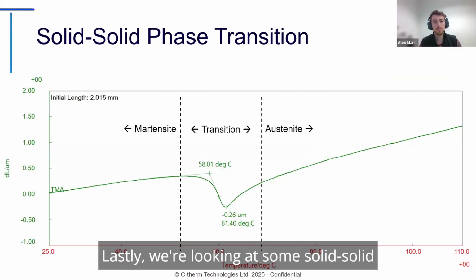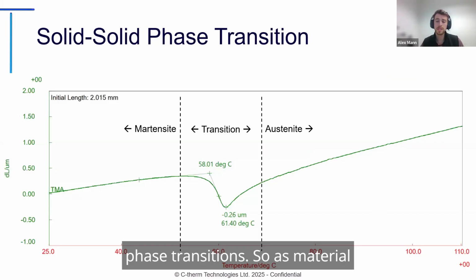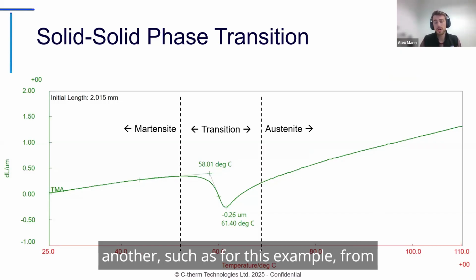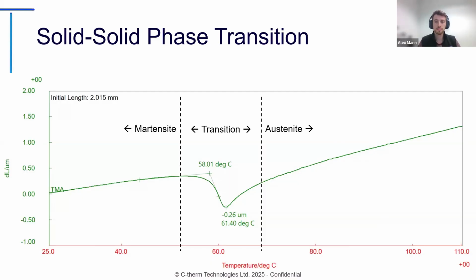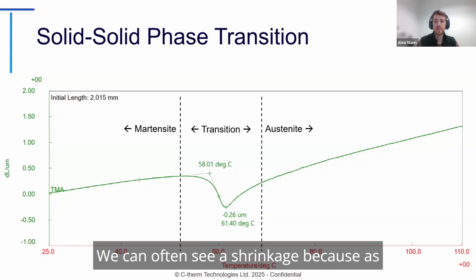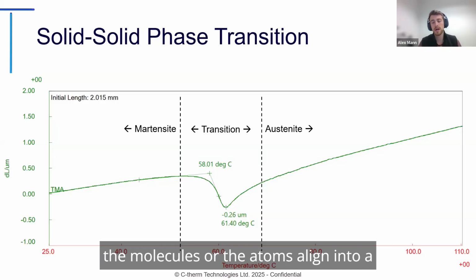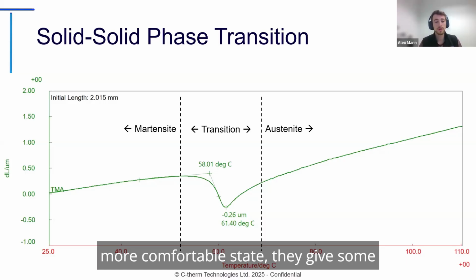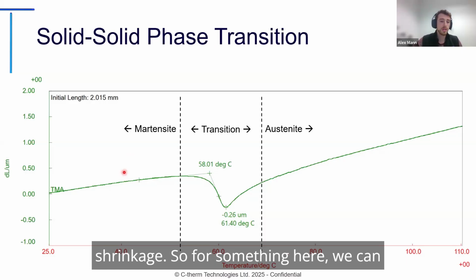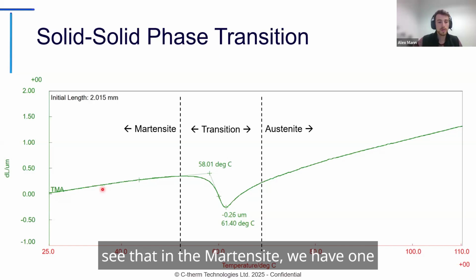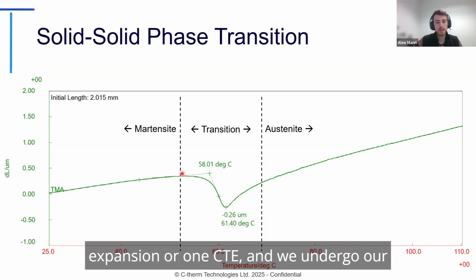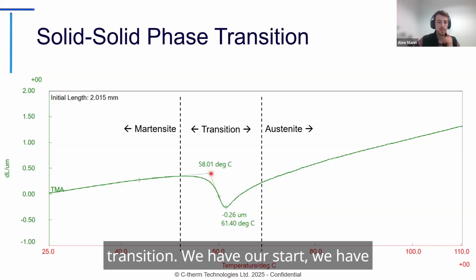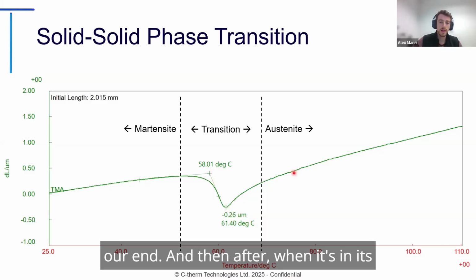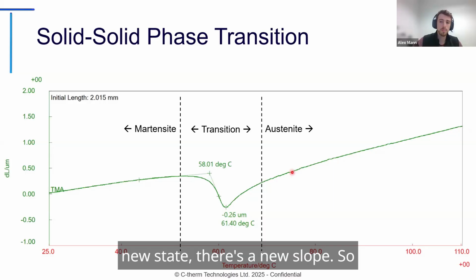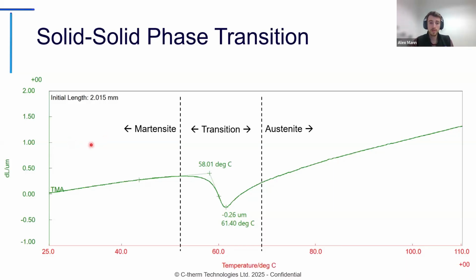Lastly, we're looking at some solid-solid phase transitions. So as material undergoes a change from one state to another, such as for this example, from its martensite to its austenite, we can often see a shrinkage because as the molecules or the atoms align into a more comfortable state, they give some shrinkage. So for something here, we can see that in the martensite, we have one expansion or one CTE, and we undergo our transition. We have our start, we have our end, and then after, when it's in its new state, there's a new slope. So there's a new rate of expansion. So that's something else we can do.